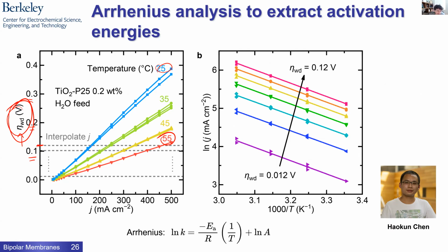So if I extrapolated at a constant driving force, a constant voltage, for different temperatures, I can then take those points and build Arrhenius curves. Okay, and I can build those Arrhenius curves as a function of driving force, and all these Arrhenius plots are linear. Okay, so what that means is they all have roughly the same activation energy. And what's changing is the intercept, okay? So the prefactor, or sort of attempt frequency, one might think, from a simple general chemistry perspective. And this was actually kind of surprising, okay?